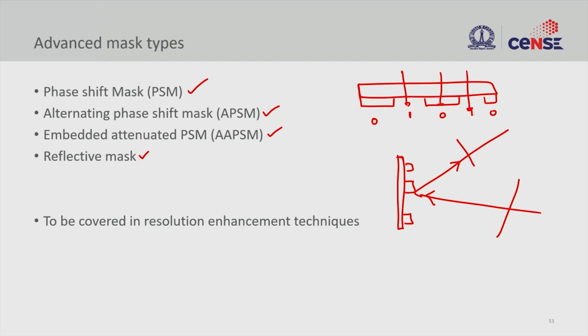So with this we come to the end of how we make a mask, and what are all the important features of this mask one should take care of. It is fabricated similar to the way that we transfer image onto the wafer. The only difference is we don't do printing here. Printing always requires a template. So here we use a writing process. Either we use a focused LED or a focused laser to write patterns on this resist coated mask. And in advanced lithography masks, where your structures are very small, we use electron beam lithography.